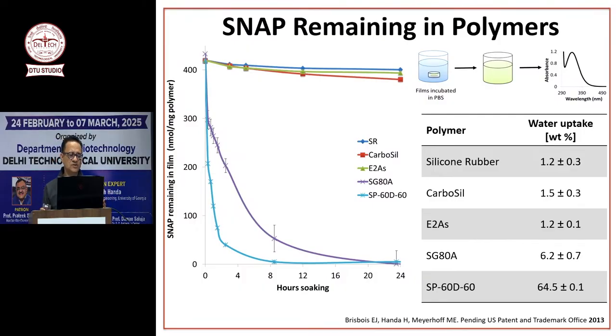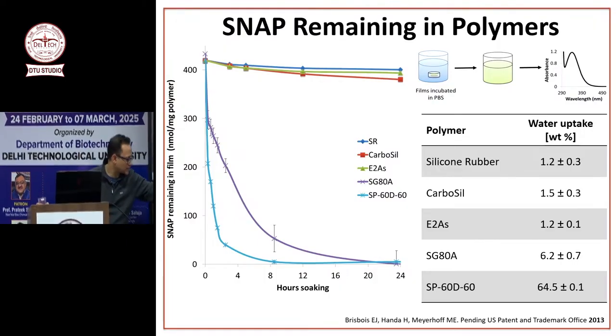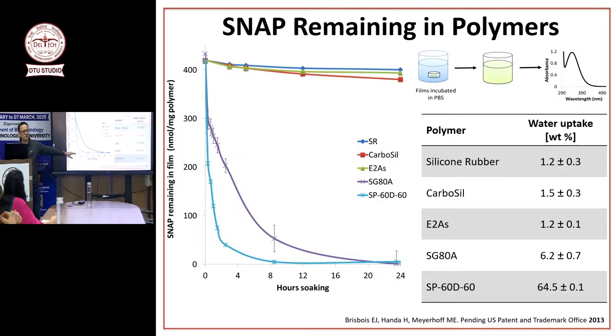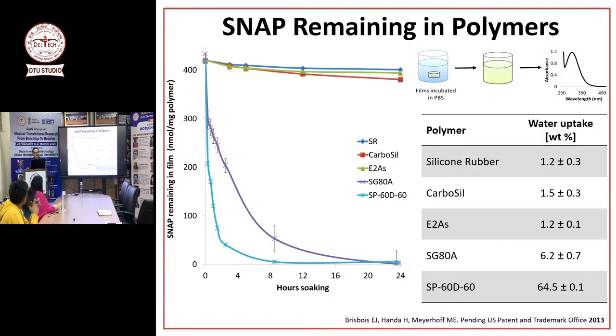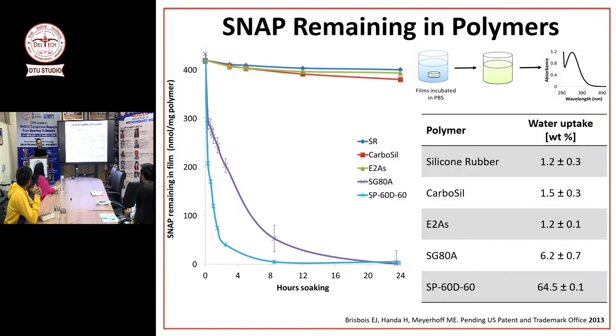So what we did in the first study was, we made a solution of different polymers and put SNAP in it. SNAP is a NO donor. We don't need PLGA and all that now, so forget PLGA. And we cast films and put them in buffer for 24 hours. What we saw with UV-vis is that with SG80A and SP60D60, all the NO donor leached out within 24 hours. Very fast. In 4 to 8 hours, most of the NO donor was leached out. So those are not good candidates for us. I don't want my NO donor to leach out. But the other three were really good. They almost kept all the NO donor inside. For the others, because the water uptake was so high, water was entering inside and bringing all the NO donor out.